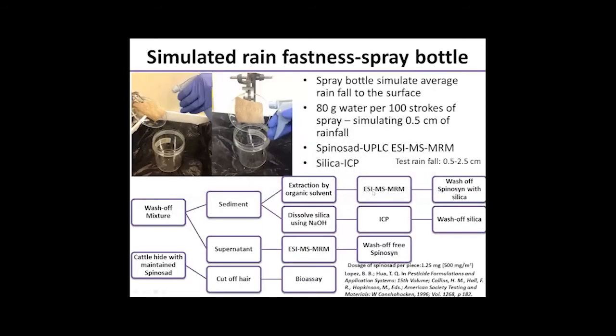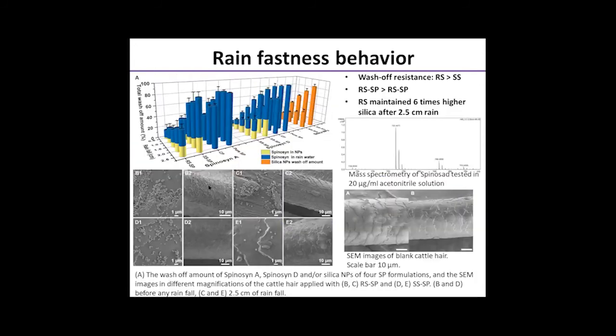In field applications, the effective duration of spinosad applied on cattle is largely affected by weather conditions, especially by the rainfall. The rain fastness test was chosen to quantitatively measure this effect. A modified spray bottle protocol was used to test the rain fastness property of 4 spinosad formulations using artificial rain. The wash-off amount of silicon nanocarriers and the spinosad active components, for example spinosad A and spinosad D, were quantitatively measured using ICP-OES and ESI mass spectrometry. The results are shown in this slide.